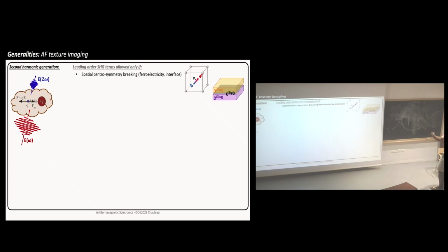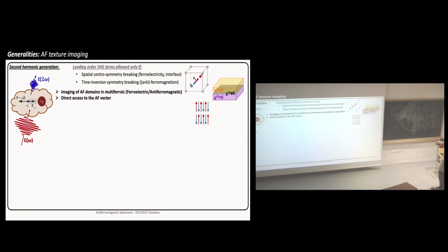But on top of this, you can add other ingredients. For example, you can add the time inversion symmetry. And what you have to know is that magnetism, to some extent, breaks the time inversion symmetry. So if you add this to second harmonic generation, then you have access to antiferromagnetism, to magnetism, let's say. This is why, for example, it has been used to image domains in multiferroics, which are both ferroelectric and antiferromagnetic, such as BFO, because they naturally break the central symmetry.